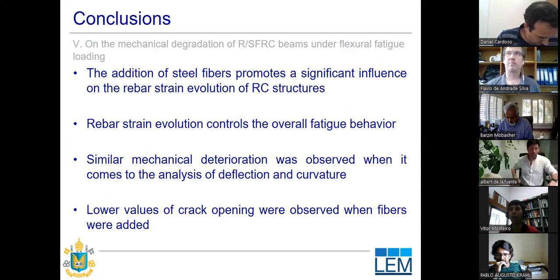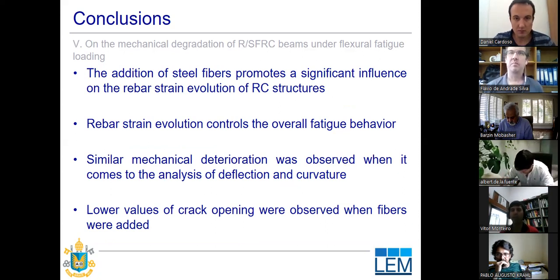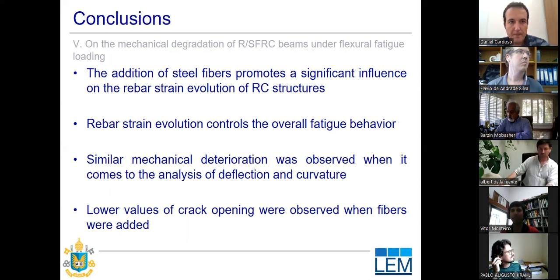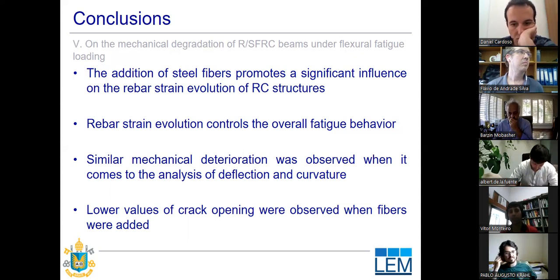So when we have more rebar strain evolving in the structural tests, it is a possible way to evaluate how the structure is degrading along the cyclic loads. The additional fibers could significantly influence the rebar strain evolution, mitigating the deterioration of the structure by redistributing the stresses in the tension zone. Similar mechanical deterioration was observed, and the use of fibers could mitigate the degradation of the major mechanical parameters of the concrete beam in the fatigue loading.